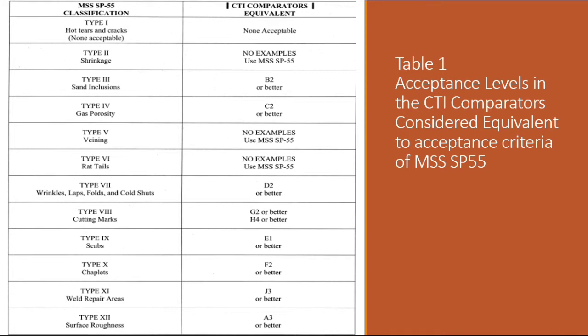Type 7, wrinkles, lap, fold, cold shut, D2 or better can be acceptable and the rest we cannot accept. Type 8, cutting marks, G2 or better or H4 or better can be acceptable. Type 9, scabs, E1 or better can be acceptable. Type 10, chaplets, F2 or better can be acceptable. Type 11, weld repair area, J3 or better can be acceptable. Type 12, surface roughness, A3 or better can be acceptable.